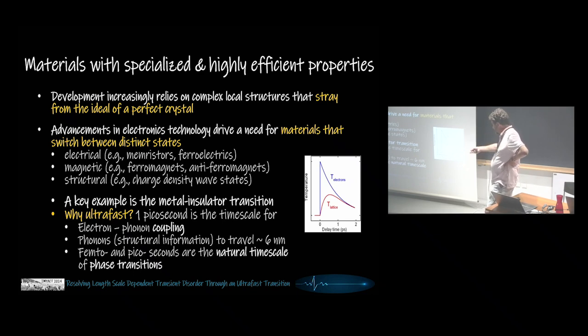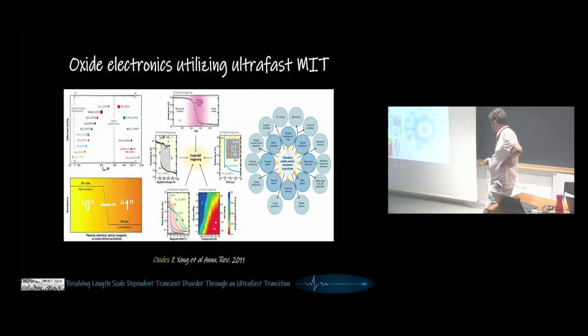Why ultrafast? Well, this was presented somewhere else, so it's for a slightly different audience. One picosecond is the time scale for electron-phonon coupling, and also femto and picoseconds are natural time scales for the electronic phase transitions. Another aspect is that oxide electronics utilizes ultrafast metal insulator transitions. There is a number of materials, a number of switching mechanisms, and a number of properties. But ultimately you have basically two states that you want to switch back and forth between.